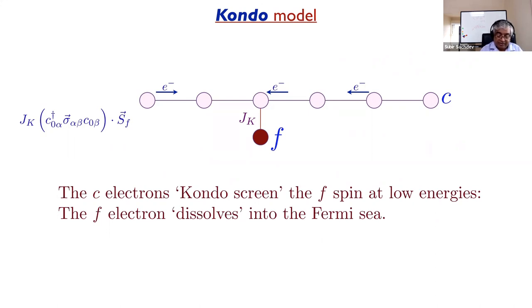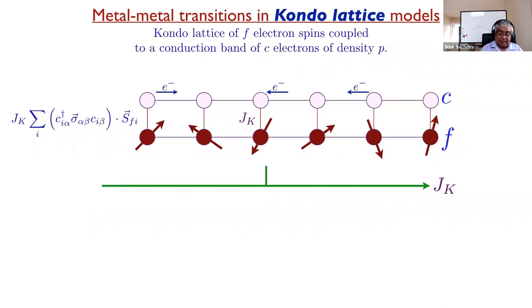But now let's consider the Kondo lattice, where you have not just one spin but a whole lattice of spins. This will be called the F band, and this is the C band. This is very appropriate for the so-called heavy fermion compounds, where there's some element like cerium or uranium, which has these spins, and then there's whatever copper and silicon, which is providing the conduction electrons. So there's really a genuine microscopic difference between the electrons that are localized because they're in F orbitals and the conduction band.